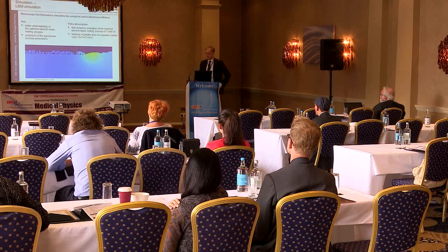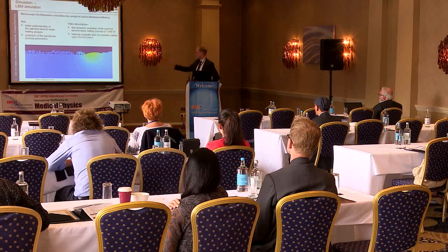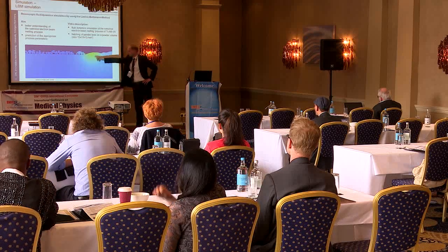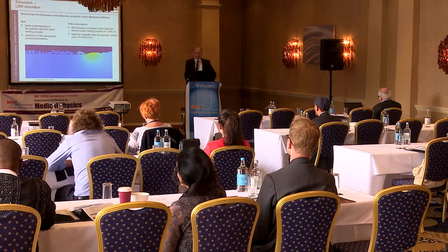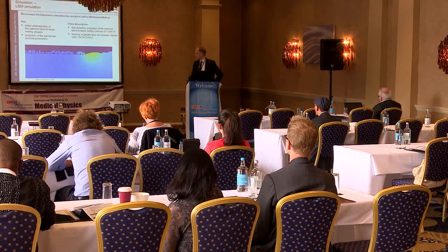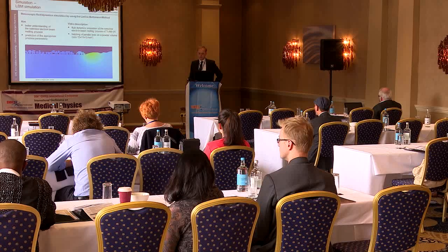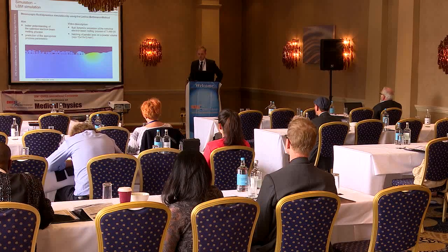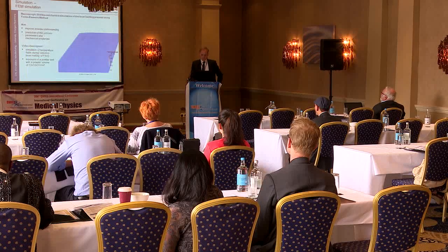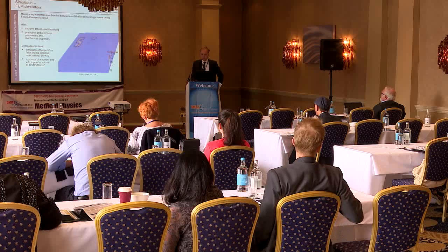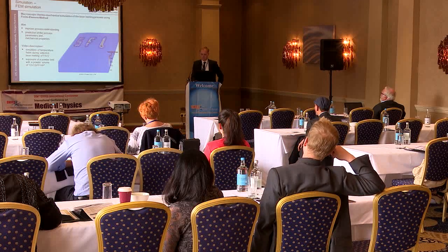Another thing is the exposure. This should also be a video, but it's not running okay. So I will show it here with the picture. Here you can see the laser beam, which penetrates into some powder particles. And with this simulation, we were able to predict where the energy input is large enough for melting the powder, as well as effects like whether the powder can fuse together, or if we have some defects in the molten state.